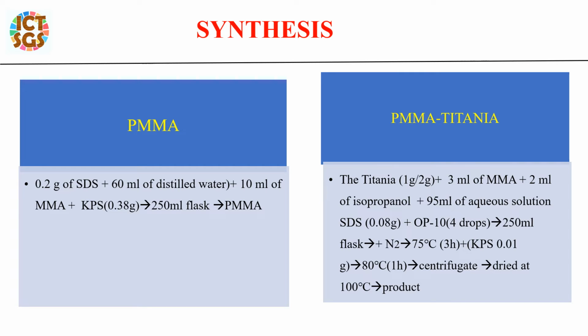Another synthesis, of PMMA titanium nanocomposites: titanium oxide, 1 gram, was dispersed in 3 ml of MMA and 2 ml of isopropanol to obtain a transparent suspension. The suspension was mixed with 95 ml of aqueous solution in which sodium dodecyl sulfate and octyl phenyl ether were dissolved, and then charged in a 250 ml three-neck round bottom flask equipped with a mechanical stirrer, a thermometer with a temperature controller, and a nitrogen inlet, for 6 minutes. The reaction mixture was heated until the reaction temperature reached 75 degrees Celsius, followed by the addition of aqueous solution of the initiator potassium persulfate, 0.01 gram, dropwise within 3 hours while maintaining 75 degrees Celsius reaction temperature. Finally, the reaction temperature was raised to 80 degrees Celsius. The stirring was continued for another 1 hour.